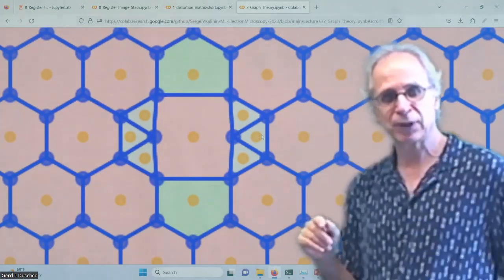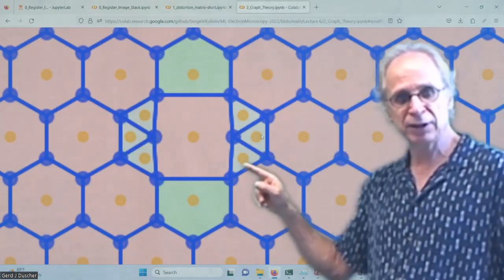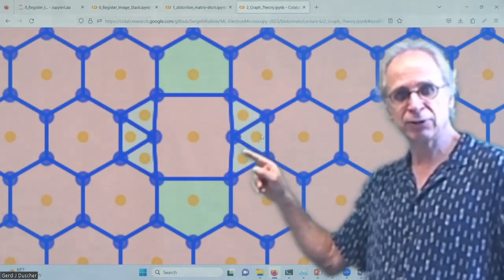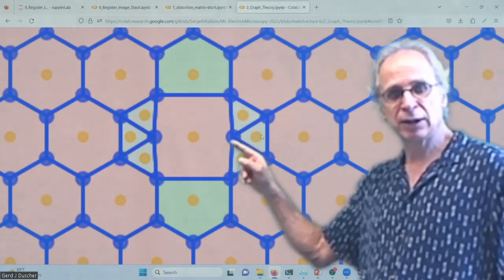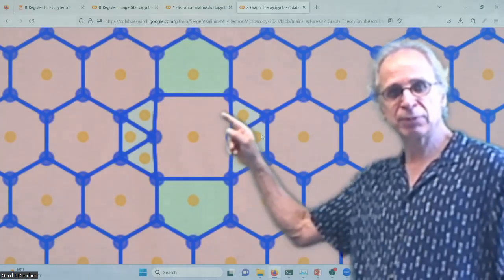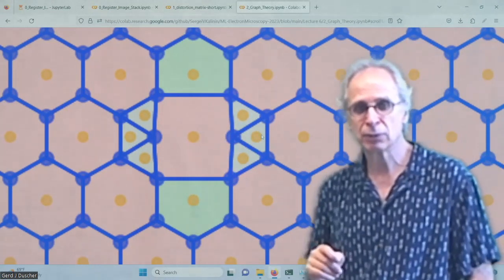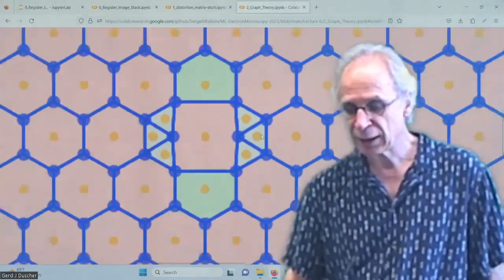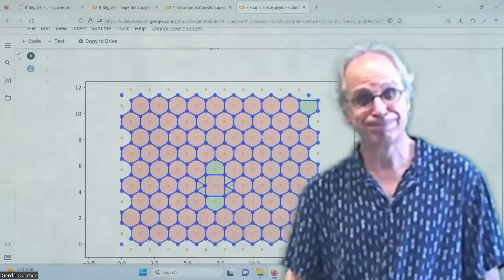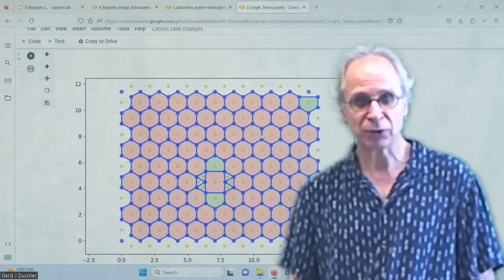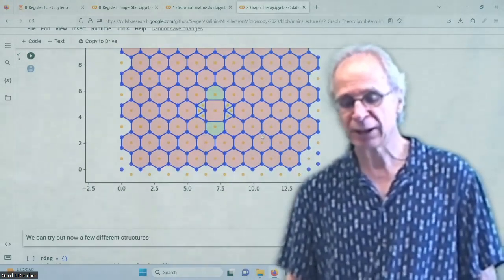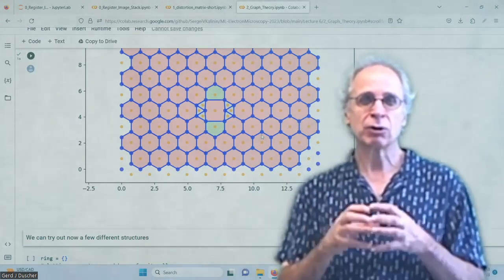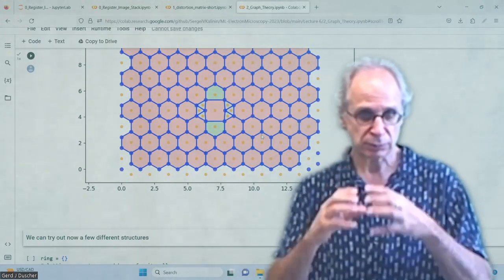It's stepped in here. And so now I have 3 triangles instead of a 5-fold ring, and this one is now a 6-fold one. Key thing is no input. And you get your bonds. And it's unambiguous. And the only thing that we are really looking for is convex polyhedra.